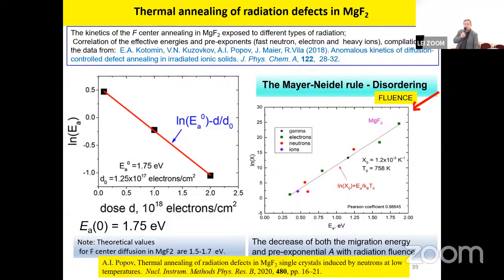Why is this important? Because in all theoretical models which are describing radiation damage, people use from the beginning the same activation energy, for example, for all point defects like interstitials. But now we know that when the lattice is changed, we also have to take into account the change of the activation energies of point defects. So the model should be more complicated than people used before.